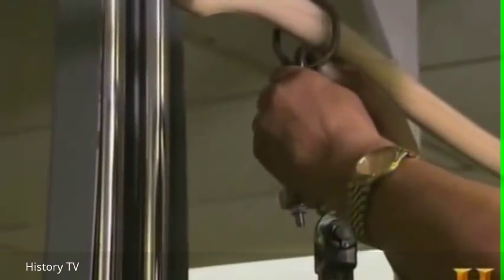Nupla periodically tests handles in this screw-driven machine that can deliver 12,000 pounds of pulling pressure. First, a new hardware store axe with a wood handle. It splinters with 244 pounds of pull on the handle. This handle broke, and it leaves a very sharp piece at this end, and the tool end itself is also very dangerous to be around. Next, a fiberglass handle. The fiberglass handle gives way at 571 pounds. More than twice the load that destroyed the wood handle. The bottom line? Fire axes with fiberglass handles almost never break, lending the firefighter's best tool a potent new dimension.